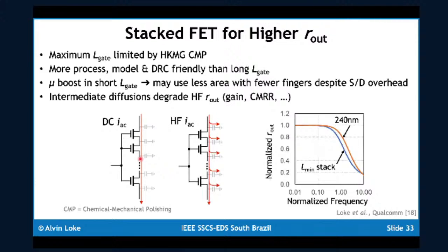Now there are some side drawbacks to that. One drawback is that these intermediate diffusions are basically capacitive AC shorts at high frequencies, which means things like your output resistance as it relates to gain, common mode rejection ratio, and so on do get degraded at higher frequency. So you can see here, if you were to use a stack of L-min devices versus a long channel device, the R out actually rolls off at a lower frequency.